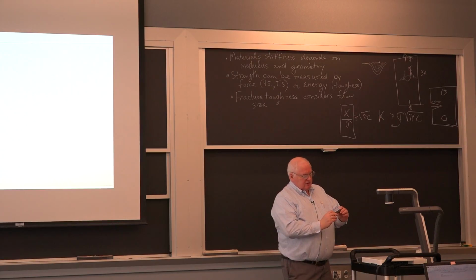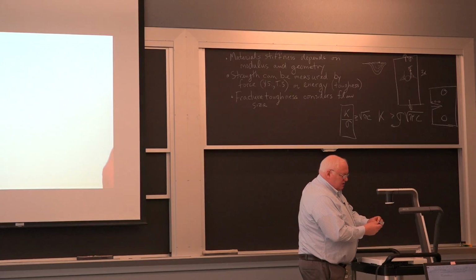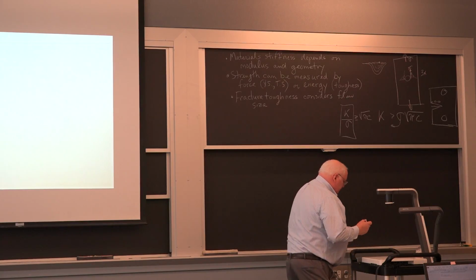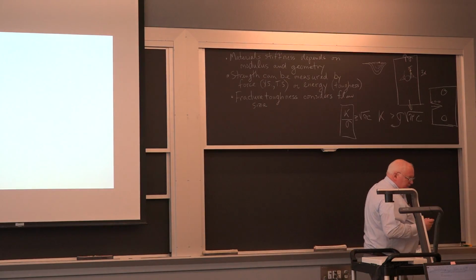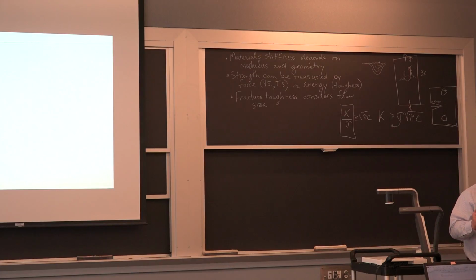And I don't know if we can still see it. This thing's getting a little old. But you have to be able to read a fracture surface. The fracture didn't go all the way through. The initial fatigue crack, this thing did fail in fatigue. And if you can read a fracture surface, you'll see kind of lines radiating that way, some other lines radiating this way. The initial fatigue crack is there at the origin, and it ran about 2/3 of the way through